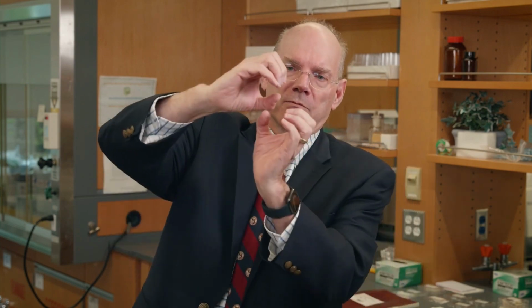Calmetrics had been making chrome calibration standards. These are very thin layers of chromium, and the trick is to make these layers very, very thin. The way their foils had been supplied was they were made by rolling. So this is a mechanical compression process. You can imagine you had a couple of rollers that are rolling like this, and you've got a chrome sheet that you feed in one side, and the rollers press it down and squeeze it down to make it very thin. And so this rolling process is a standard metallurgical process that's used for lots of different kinds of metals.